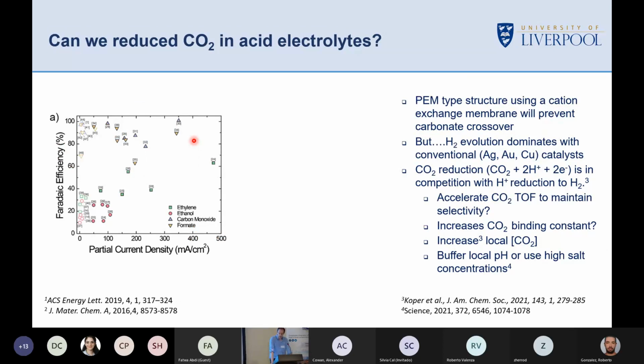I think there's a paper from Marc Koper that I'd recommend everyone has a look at, this JACS paper here. Sorry, when I turn around to look at the screen, it loses the microphone, so it's a little bit tricky. It describes a pathway potentially to work with some metal electrodes to try and do CO2 reduction. If we can utilize and decrease the local proton concentration by having our metal electrode reducing CO2, we can do this at high current densities, then potentially we can improve the Faradaic efficiency. And indeed, you can do that.